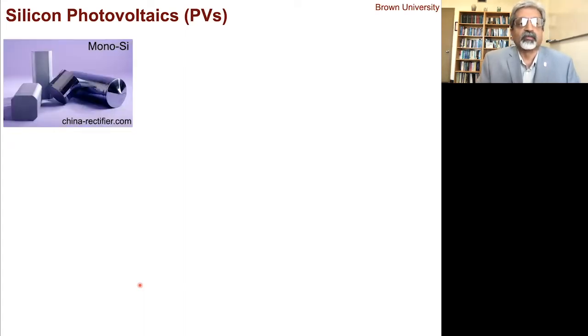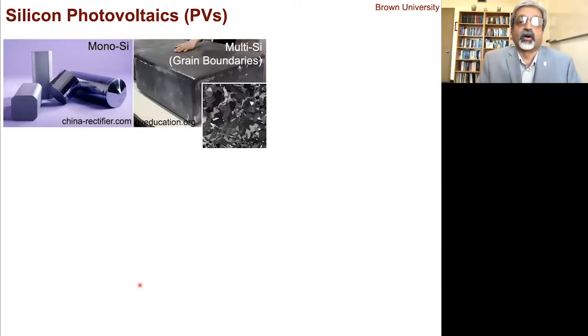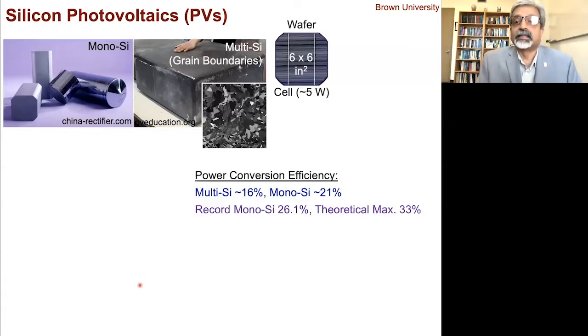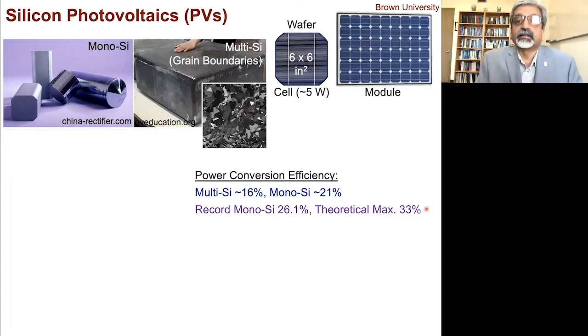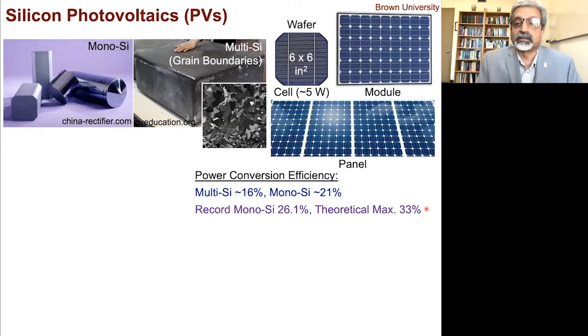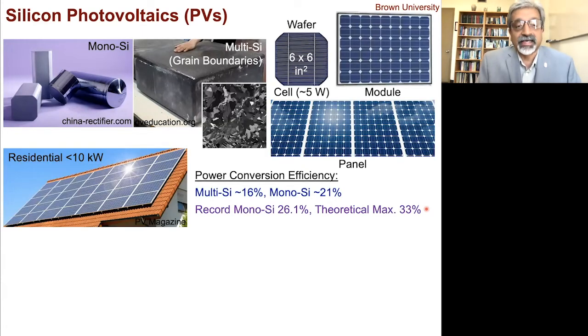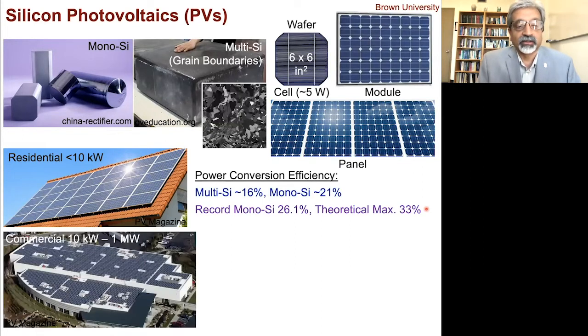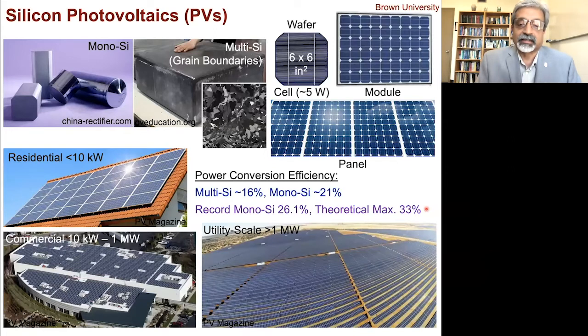So let's talk about the established technology, silicon photovoltaics. They're made from monosilicon, which is single crystal silicon, or multi-silicon, which is polycrystalline, with grain boundaries and grains. And they're fashioned into cells, which is about 5 watts per cell. The power conversion efficiency of multi-silicon is about 16%, whereas monosilicon is about 21%. This is record efficiency in lab scale cells, and the theoretical maximum based on physics is about 33%. So you string the cells together into a module, and the modules are strung together into a panel. Residential is less than 10 kilowatt, and then commercial is 10 kilowatt to about 1 megawatt. And utility scale is greater than 1 megawatt.